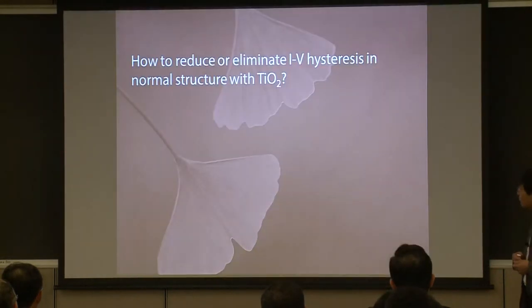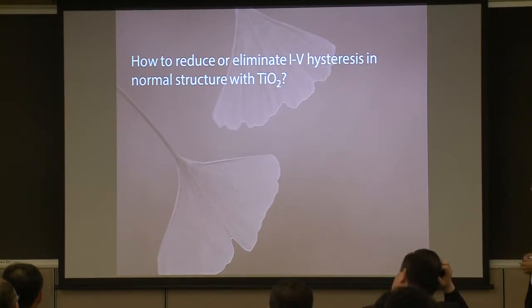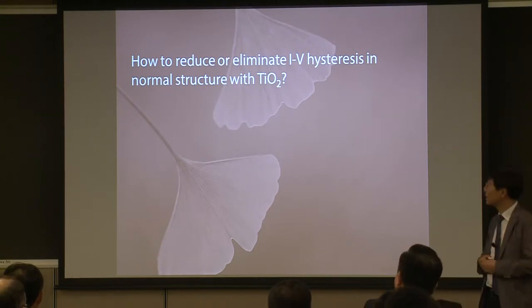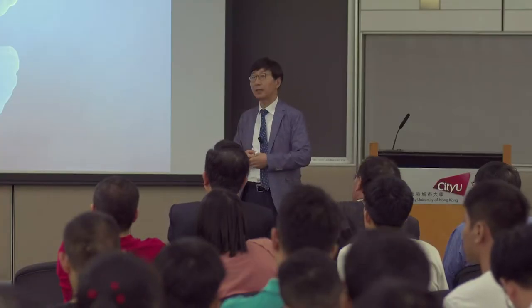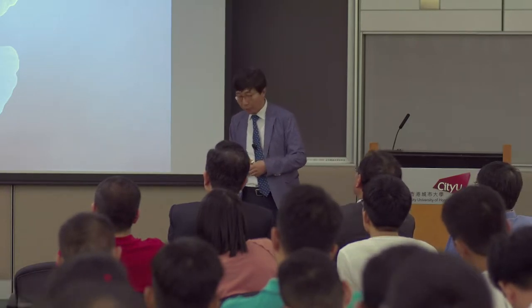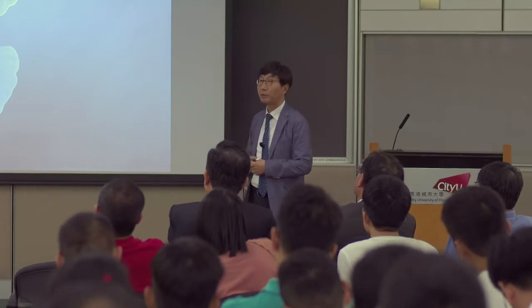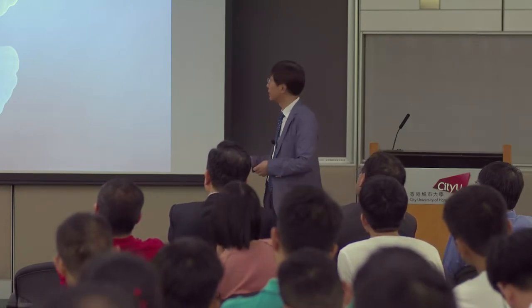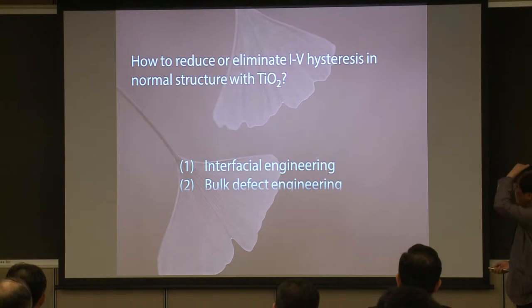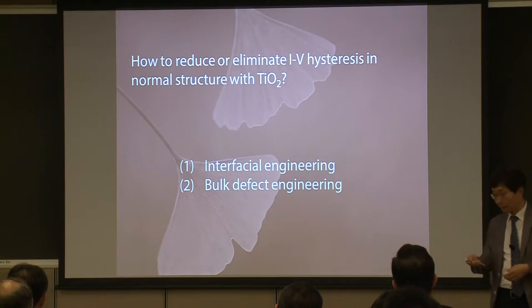So the question is then how to reduce or eliminate IV hysteresis in the normal structure containing titanium oxide. Because so far the highest efficiency was reported based on the normal mesoscopic structure containing titanium oxide, which was about 22.7% efficiency. So I'd like to introduce some interfacial engineering and also bulk defect engineering to reduce the IV hysteresis.